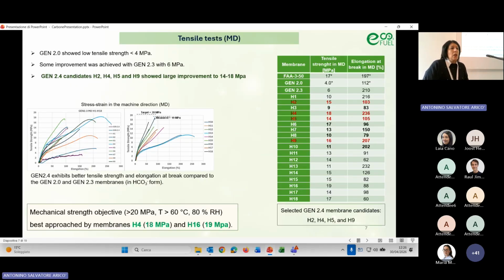So at DTU, they performed with a different instrument tensile strength in the machine direction. Here in the graph are reported all the membranes that were tested. I show with the mouse because online they can see. So all these membranes were tested, and here there is a comparative table, and we can see that only membranes H4 and H16 approach the target of the project, that is 20 megapascal at 60 degrees. This test was carried out at 60 degrees and 80% relative humidity. And according to this table, we did a selection for further characterization, and 4 membranes were selected and tested also